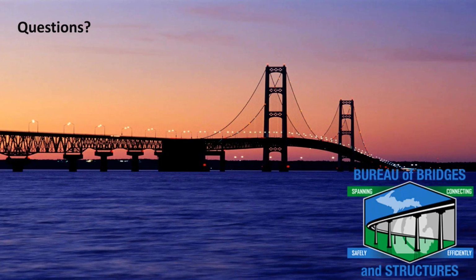Okay. You mentioned the UV resistance. Can you comment on that? Long-term performance? Yeah, so obviously these types of repairs aren't exposed directly to sunlight. They're typically under the bridge. But as Steve mentioned, the epoxy that we actually use, or the resin that we use to impregnate the fibers, that contains UV inhibitors, and then the finished concrete surface coating that we apply over the FRP system, that also has a UV protection system in it. So it is an issue for FRP materials. They do degrade due to ultraviolet light, but by coating them, we're effectively protecting them.